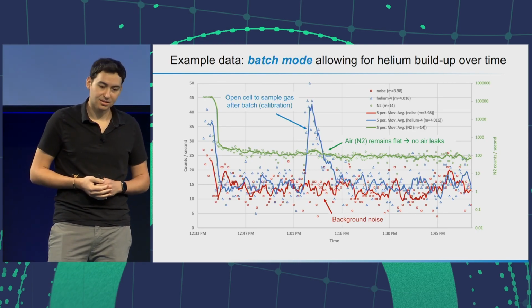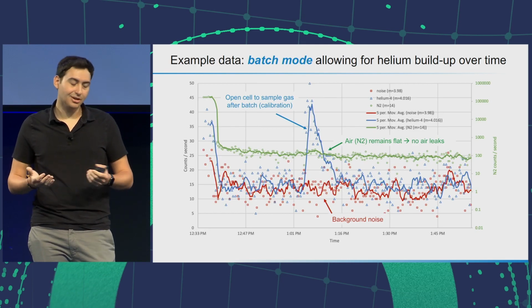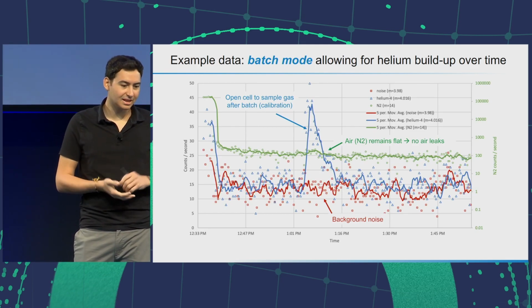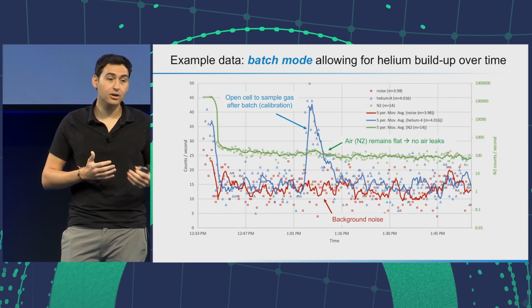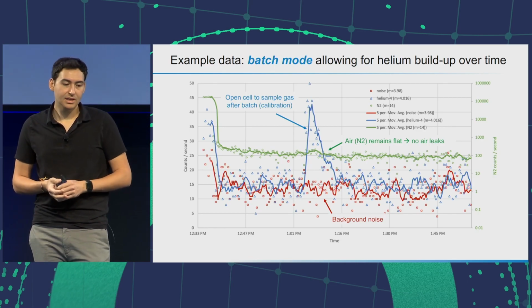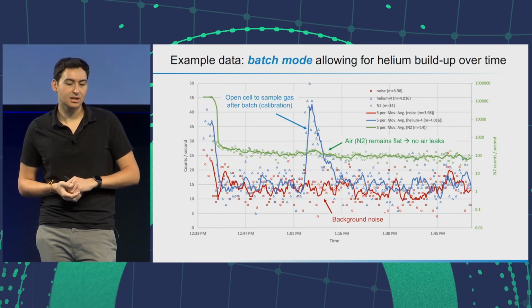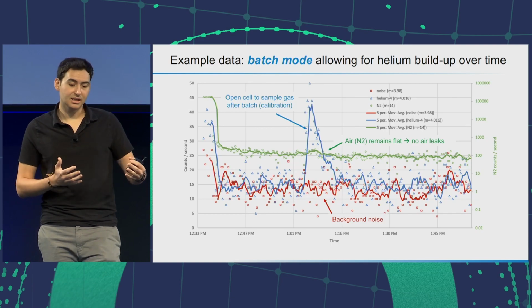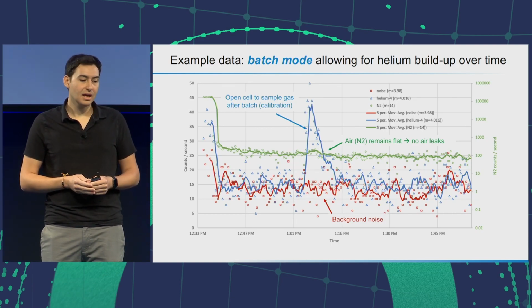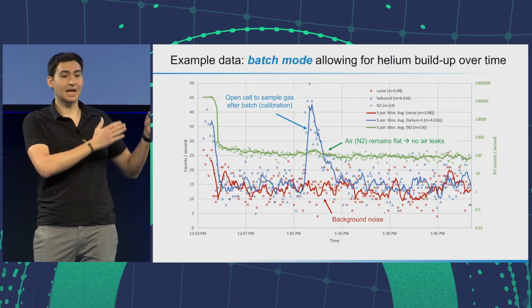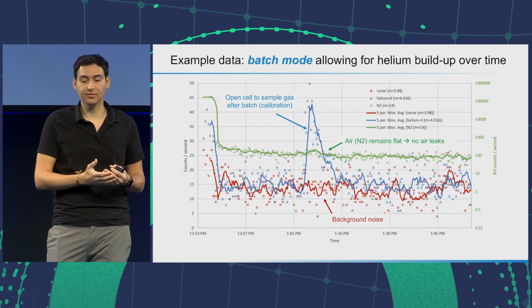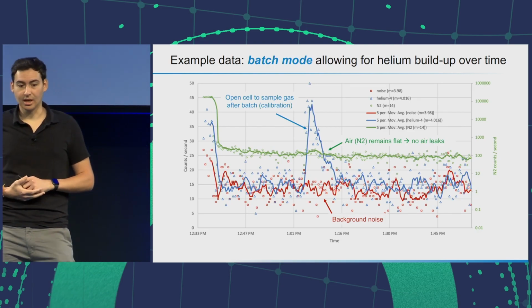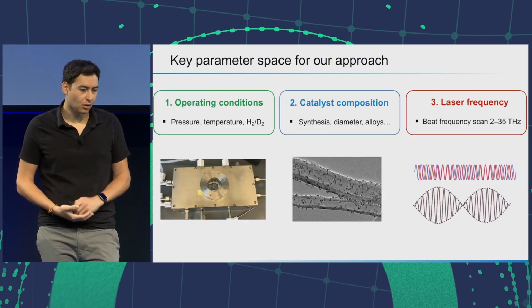And you could see there's not really a bump in air. It's on a log scale, so there's a little bump, but we've looked at enough of this that we have confidence there's no air contamination entering our system. And so we have the real-time analysis, we have this batch analysis, and by studying air, making sure there's no contamination, and taking this data and then looking at the profile information to really confirm, that's what constitutes a smoking gun, at least for our approach.